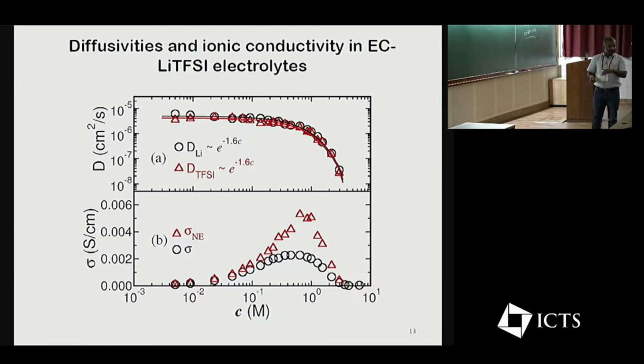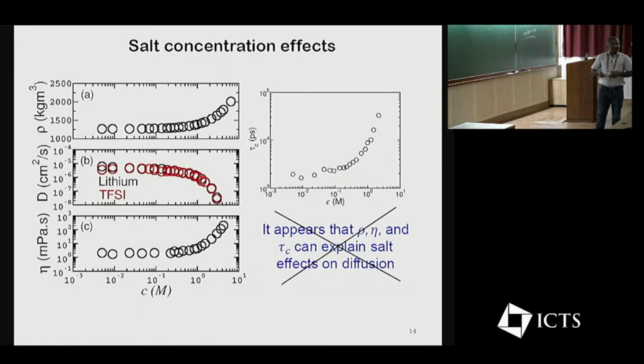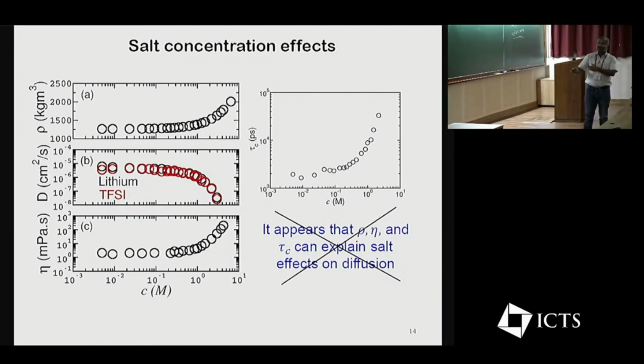So let me go directly to the results. We have the diffusion coefficient, which goes down with the salt concentration, but conductivity goes up and down. Eventually, at high salt concentration, conductivity goes down completely. So it looks like, from other analyses like density, viscosity, or the relaxation phenomena, it looks like the